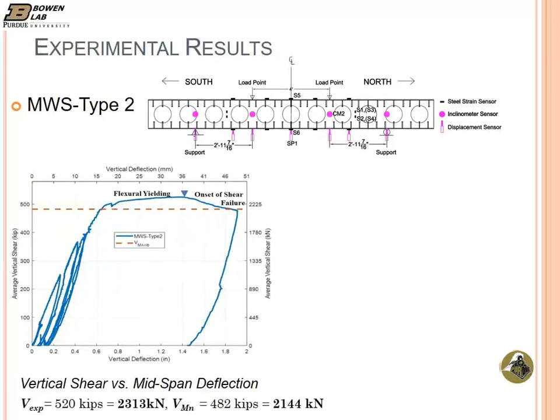The strength was 2,300 kilonewtons, and the code calculated flexural strength. Since this specimen also failed in flexural yielding, we compared it with the flexural strength, which is 2144. That's also shown up here. And this equation accounts for the web plate contribution. So the code was conservatively estimating the strength of the specimen also.